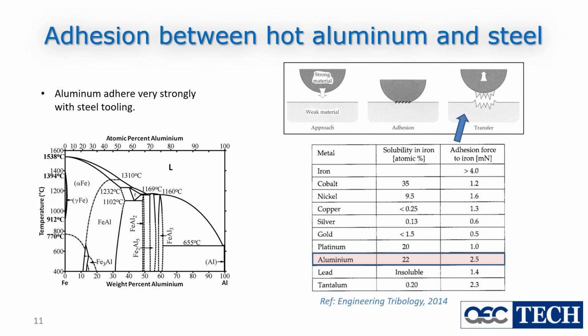So aluminum adheres very strongly with the steel. That's why we have adhesive wear. And I put an aluminum-iron phase diagram here to just show how much aluminum we can dissolve in iron without making a new phase. For example, alpha iron has up to 20% capacity to dissolve aluminum in it.